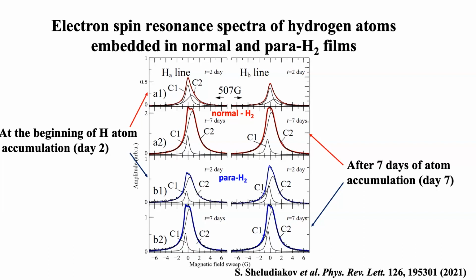First, you can see the signal can be represented as the sum of two lines: one narrow line and one broad line. What we saw after the second day was that the narrow line doesn't change in each experiment; only the broad line changes. Also, after the second day, the line width of the broad line doesn't change, only the intensity increases. I will show this in a following slide.